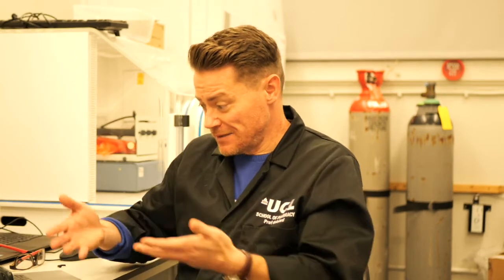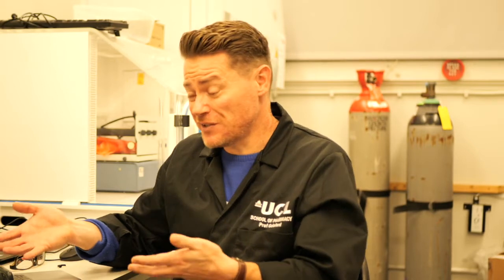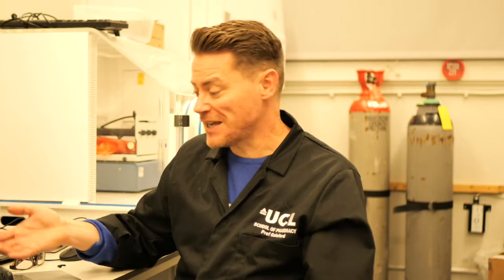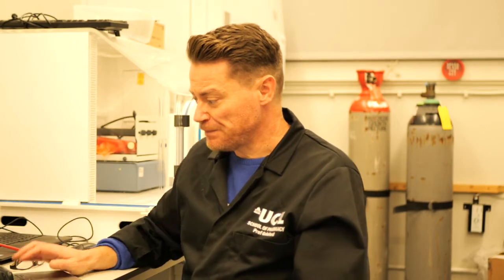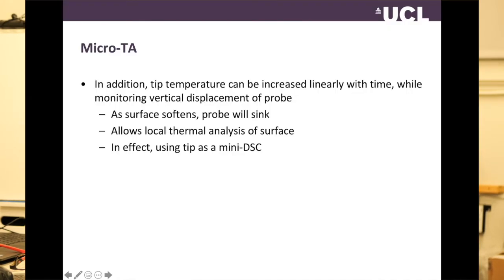So in the indomethacin tablet, the chances are that's a particle of indomethacin exposed at the surface of the tablet, but other than saying it's got a different thermal conductivity, it's quite difficult to say for certain that is definitely indomethacin. One of the beauties of this type of tip is that it's measuring resistance by passing a current through it, and you can measure thermal conductivity in this way. But as I'm sure you're aware, if you pass a current through a metal wire, it heats up. It's the principle of how your toaster toasts your bread in the morning. And this works the same way.